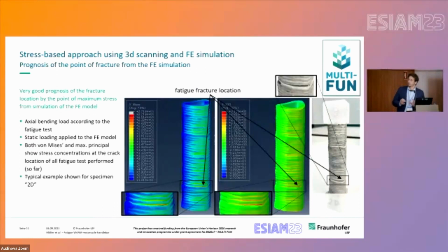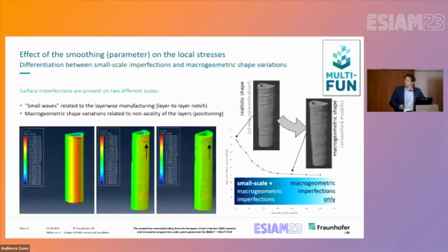So we can take a look through von Mises stresses or maximum principal stresses. In this case, both give us the information on the maximum stressed area of the specimen, which is afterwards also the crack location in our fatigue test. So there's a good correlation between the numerical simulation here and the fatigue crack location afterwards. This was not just the case for this single specimen, but also for the other specimens we tested. Which is a first good start.